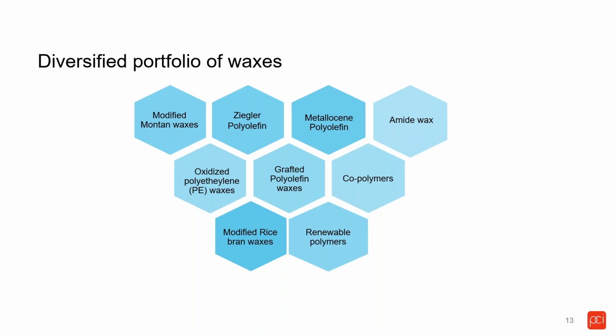This is our product line that we call Advanced Surface Solutions, basically a fancy name for waxes, but it's because for coatings and inks applications, we're modifying surface properties with these types of waxes. So the ones you see on the screen here are the base waxes that we manufacture, blend, modify, and so forth. And then the micronized waxes is really what's the most common product that we would use in coatings and inks. And these are going to be micronized to specific particle size, D50 ranges. And that's where we're typically using the micronized type of wax in coatings and inks.